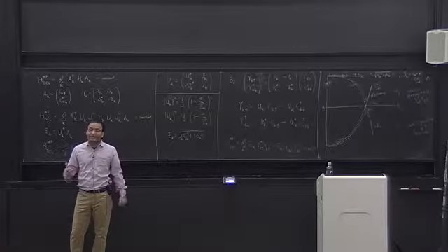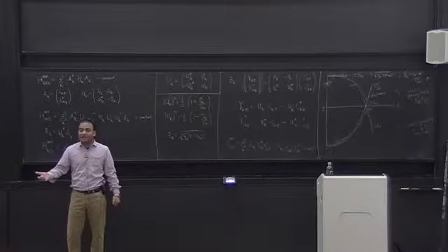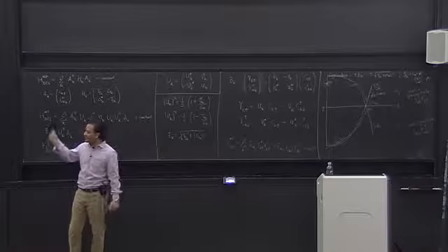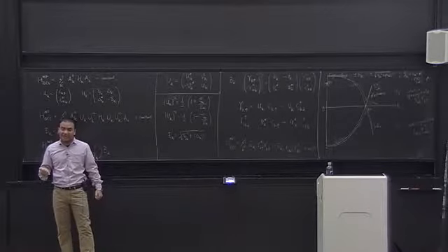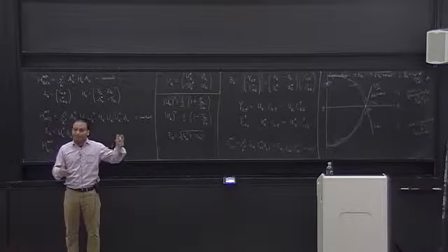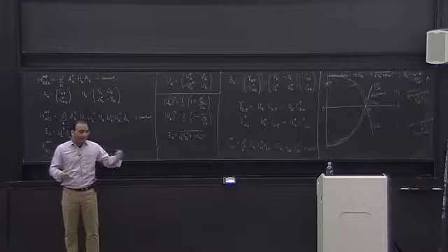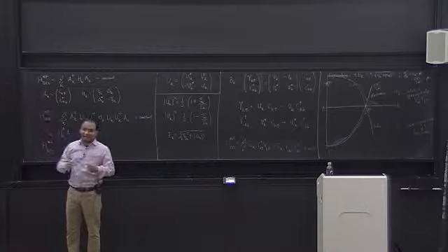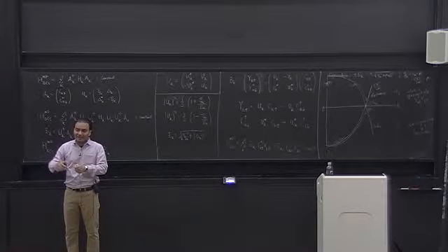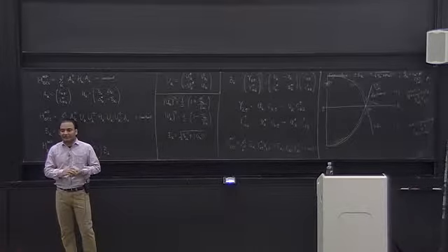You can understand this because the wave function for the superconductor only conserves parity, which means it only conserves the number of particles modulo 2. So if you start with even, because it has these two creation operators, two annihilation operators, that means if you have one electron, this is actually also the same as one hole with a coupling. And this coupling is described by a process where you take one electron, take another electron, make a Cooper pair. And in this process, you've actually created a hole. And this process provides the coupling between the two.